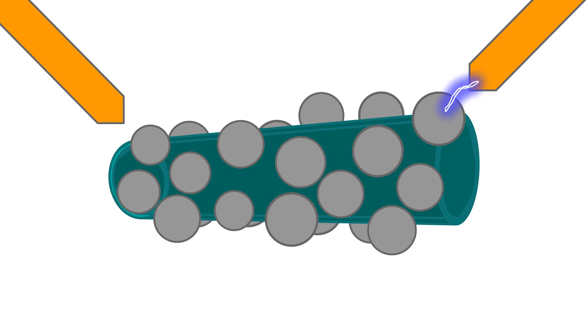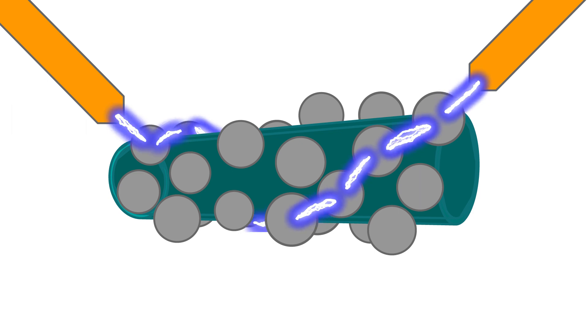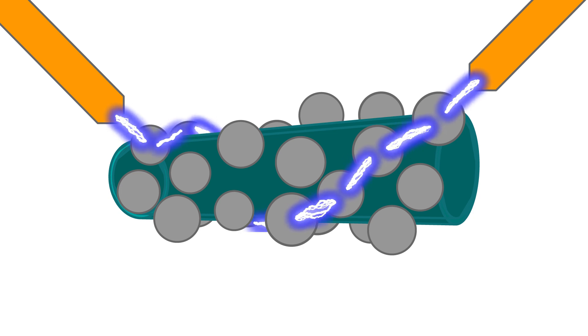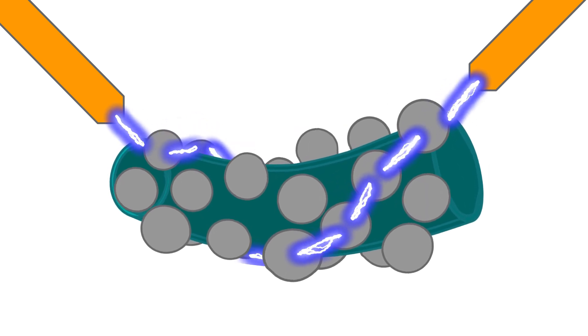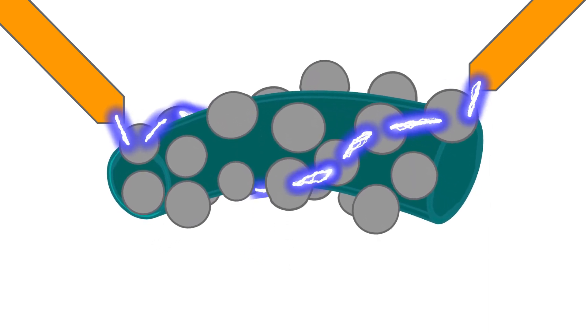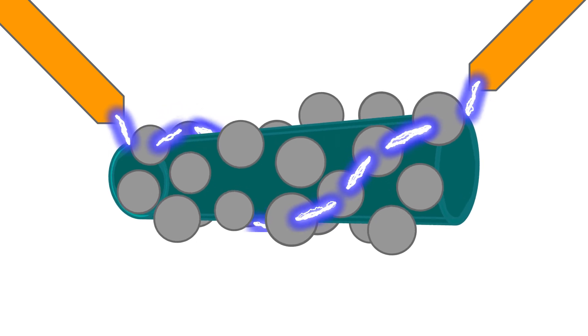Because of this uniform distribution, whenever you bend the nanotubes or leave them unbent, electrons are able to find a similar path across the nanotubes. When we bent them at different angles, we found that the current flow across this new transistor behaves the same. This result suggests that this is a new flexible channel for future flexible electronics.